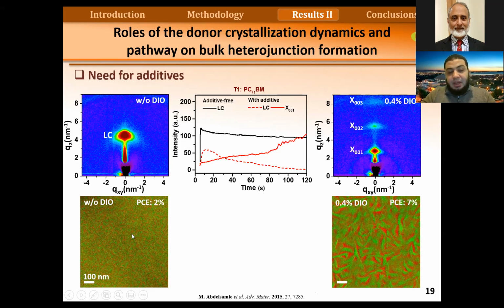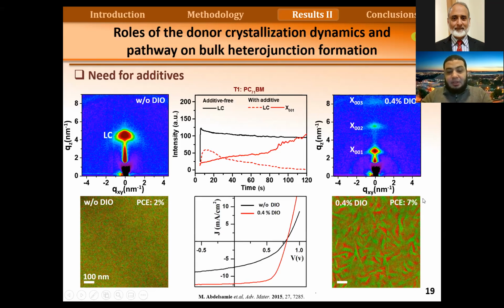The one on the left has very poor phase separation. The donor and acceptor materials are mixed, so this material cannot extract the charges efficiently. But for the one on the right, because we have sufficient phase separation, we can extract the charges. We get more than a 3 times increase in efficiency, as we can see here from the device performance.